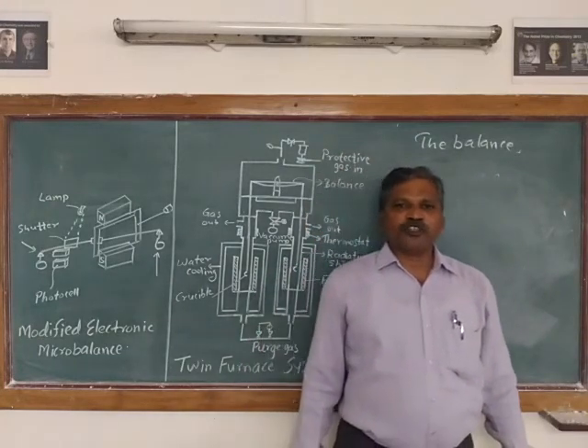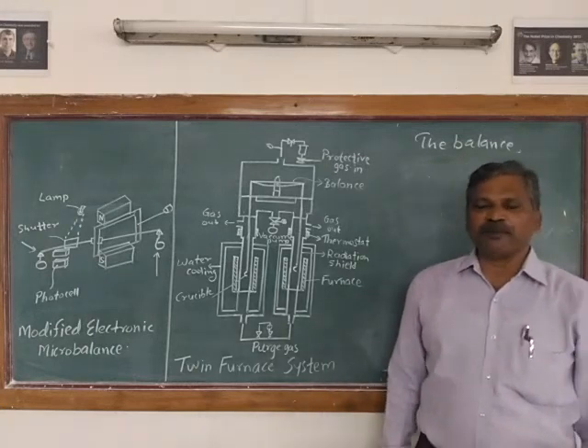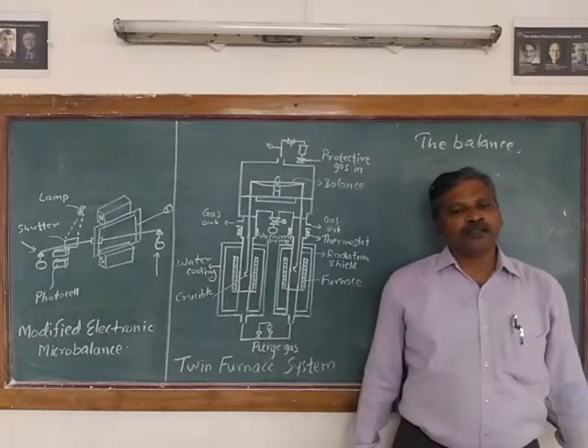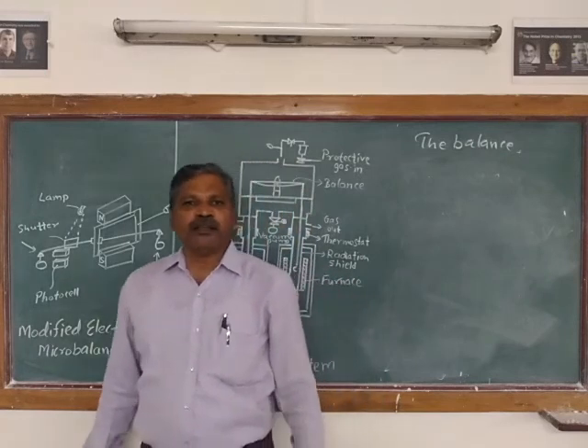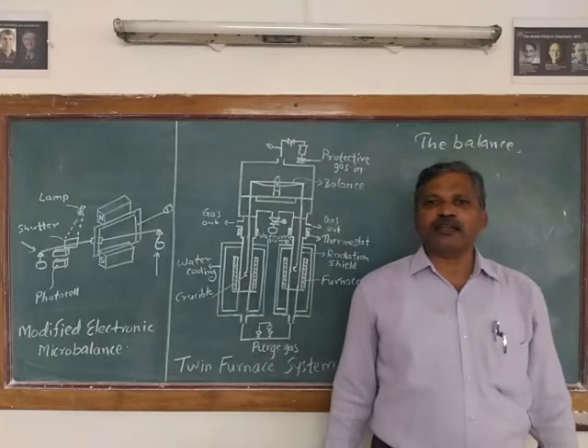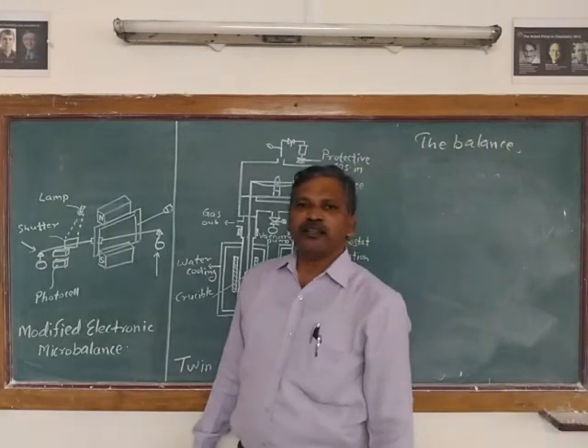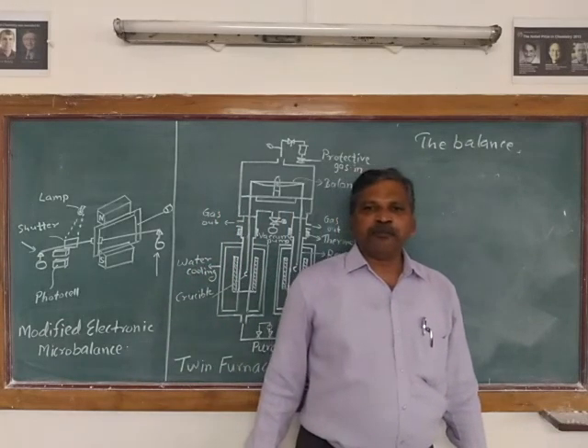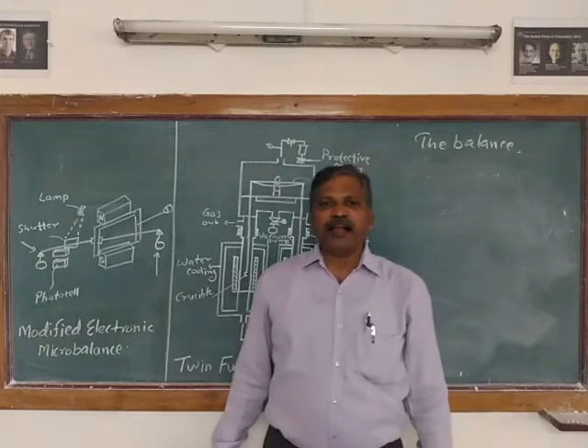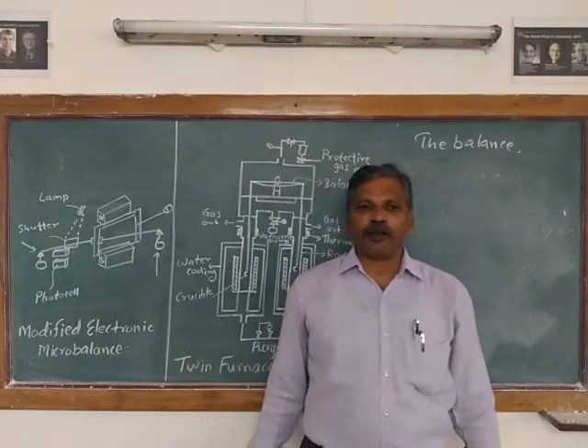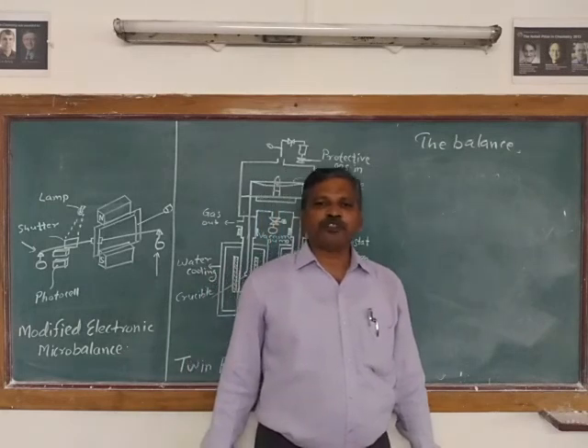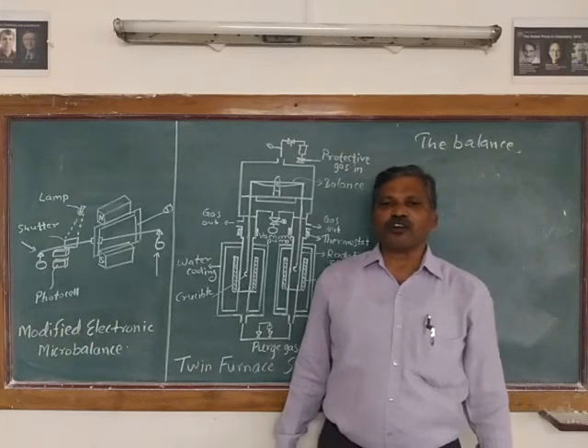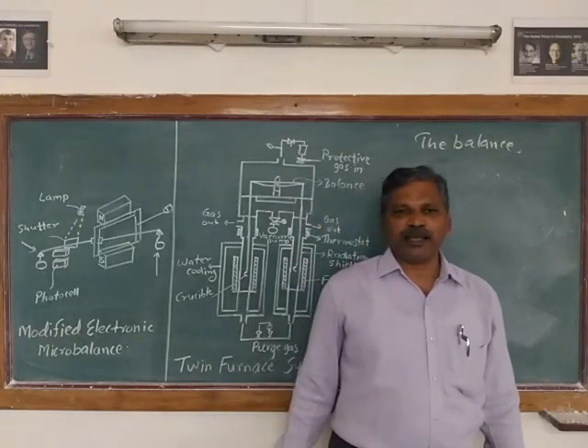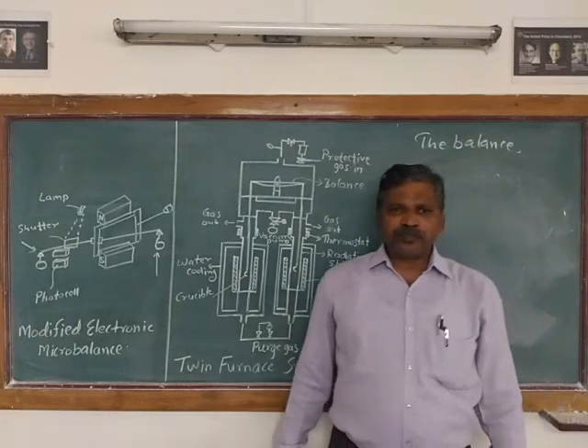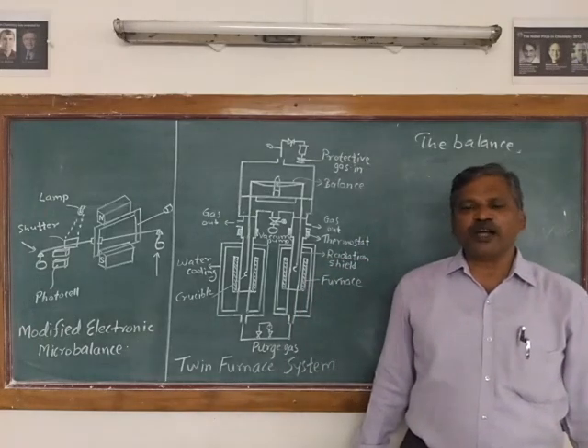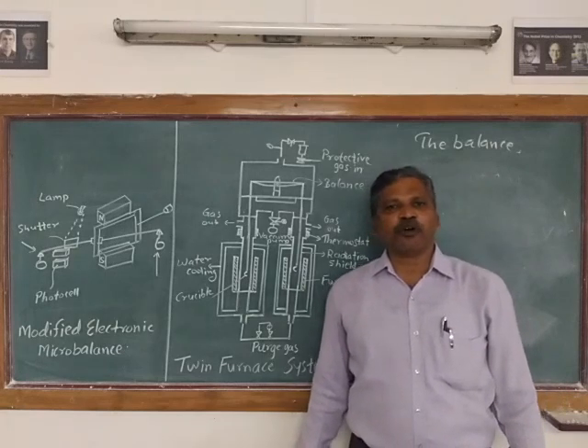Thermogravimetry in very corrosive atmosphere may be carried out by using a magnetically suspended balance. In this magnetically suspended balance, the arm of the balance is going through the electromagnet. An electromagnet suspended from the microbalance holds the glass encased permanent magnet in the measuring cell. The sample in the furnace is connected by a suspension wire to the permanent magnet, and each mass change is transmitted back without contact. This allows the use of very reactive atmospheres or of samples which produce corrosive or toxic products without their coming into contact with the balance mechanism. So by making use of the magnetically suspended balance, we can handle the corrosive atmosphere which is generated due to the heating of the sample in the thermogravimetric analysis measurement.